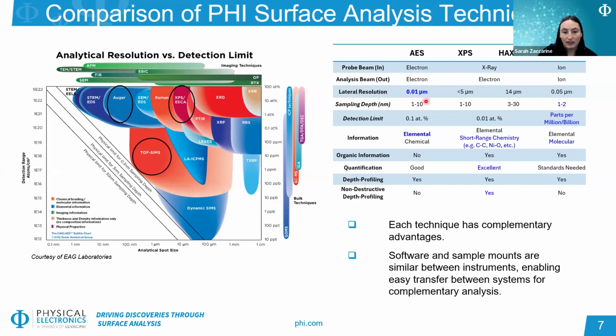So Auger generally is used for very high spatial resolution imaging and mapping of morphology and elements. XPS can also provide short-range chemical information, certain bonding types, and look at different oxidation states, as well as excellent quantification without the use of standards needed. And TOF-SIMS is the most surface-sensitive of these techniques, and it also has a really good detection limit in the parts per million or billion range, as well as the ability to get more information about molecular organic species that are present. So we're going to be showing you today how each of these techniques can be used to provide complementary information to get a more full understanding of this type of sample set. And we're going to start with Auger.